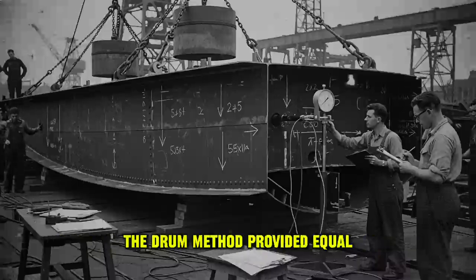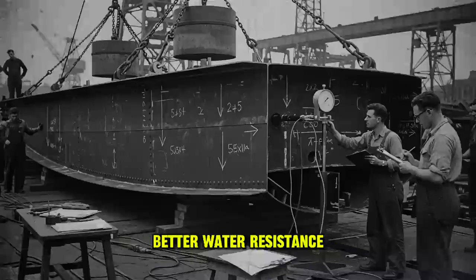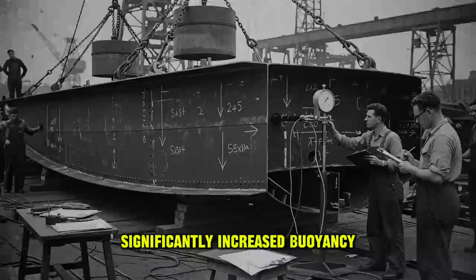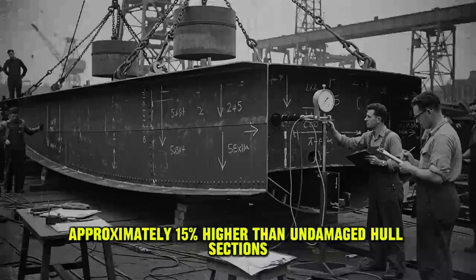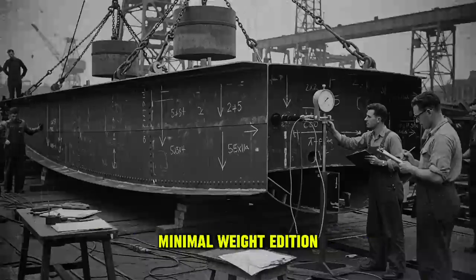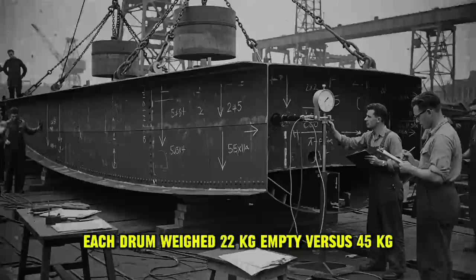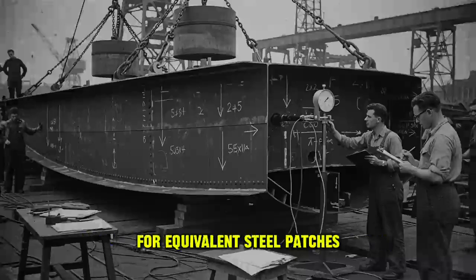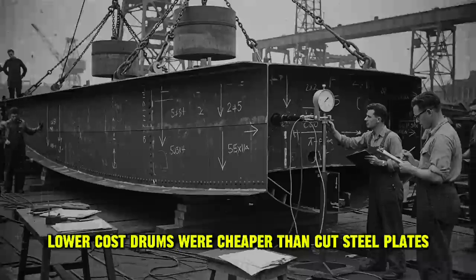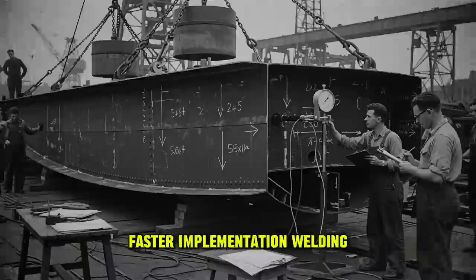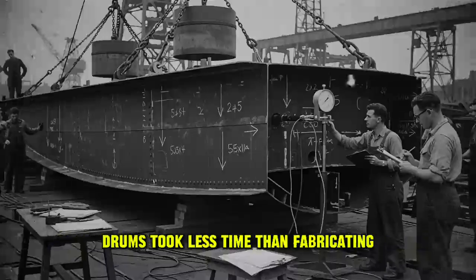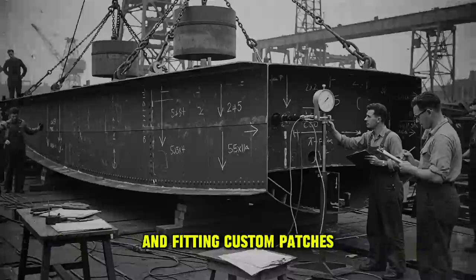The drum method provided equal or superior structural strength, better water resistance, significantly increased buoyancy, approximately 15% higher than undamaged hull sections. Minimal weight addition. Each drum weighed 22 kilograms empty versus 45 kilograms for equivalent steel patches. Lower cost. Drums were cheaper than cut steel plates. Faster implementation. Welding drums took less time than fabricating and fitting custom patches.